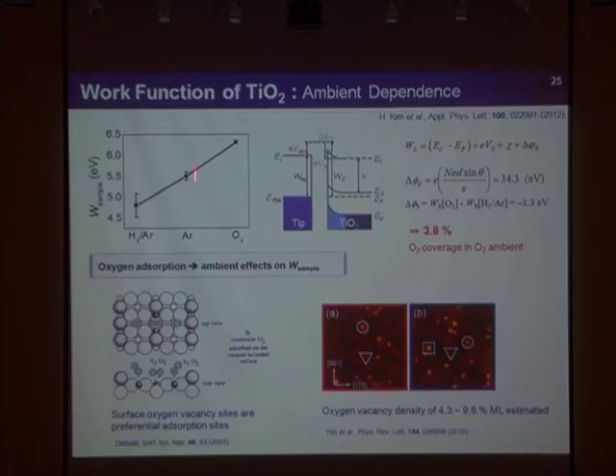From these differences, I estimated the amount of oxygen gas coverage on the surface is roughly 4%. From the literature, it's known that oxygen gas is preferentially adsorbed at the vacancy sites, and the oxygen vacancy amount is in this range after similar heat treatments. So this value is really reasonable.